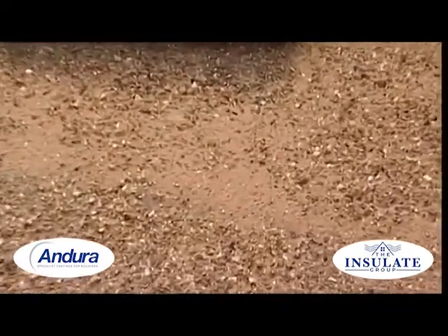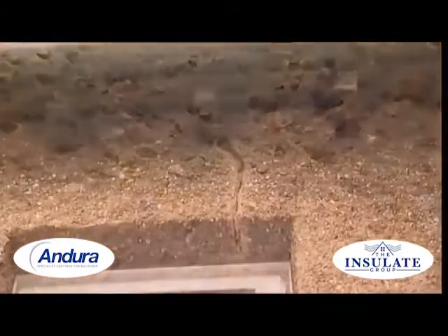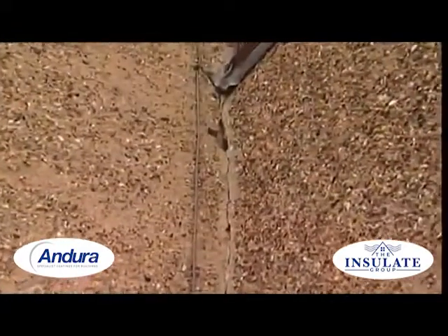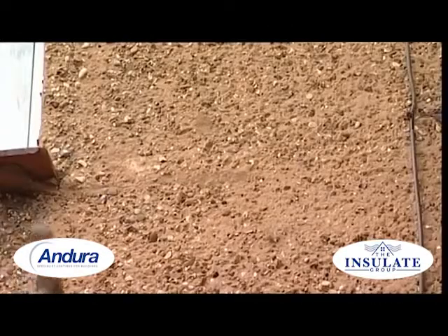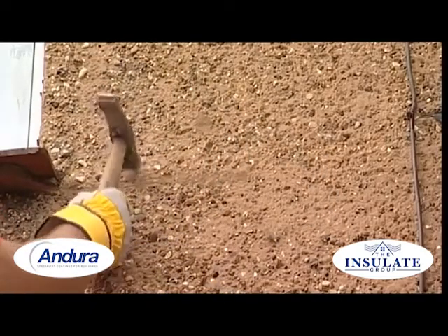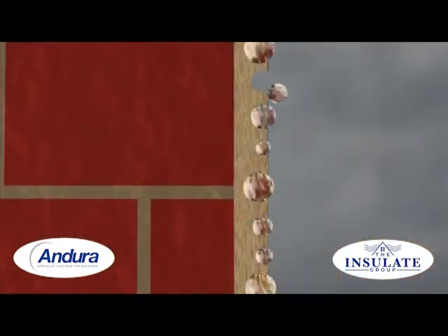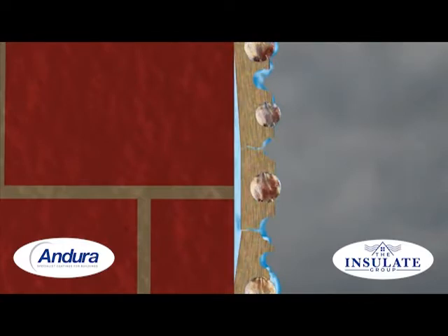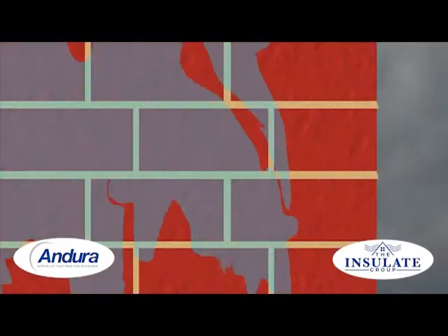Here, pebble dash, which is basically render with pebbles applied to it, is in some areas becoming quite bare. This is called destoning. And on this building, there are different size cracks. Some of the cracks have been poorly repaired in the past and simply failed again. When we tap the pebble dash, any sound differences suggest there are hollows beneath the surface where it has come away or blown. This is what happens when pebbles become loose and fall out, leaving sizeable pits in the surface. Water finds its way into these pits, and when it freezes, it does exactly the same as it does to render, forcing it away from the wall behind. The water and frost has the same damaging effect.